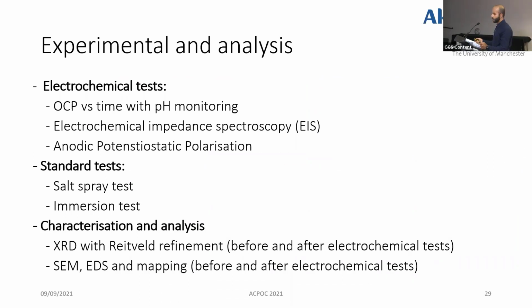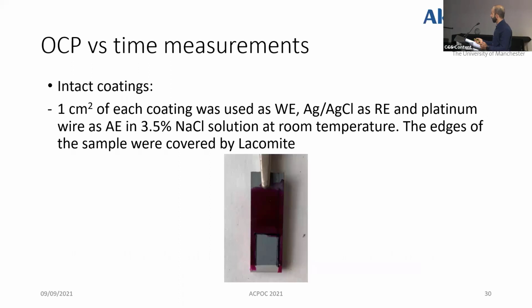This work included electrochemical tests like OCP versus time with pH monitoring, electrochemical impedance spectroscopy, anodic potentiostatic polarization, and the standard tests include salt spray test and immersion test. The characterization and analysis part includes XRD with Rietveld refinement before and after electrochemical test, and SEM, EDS, and mapping also before and after electrochemical test.